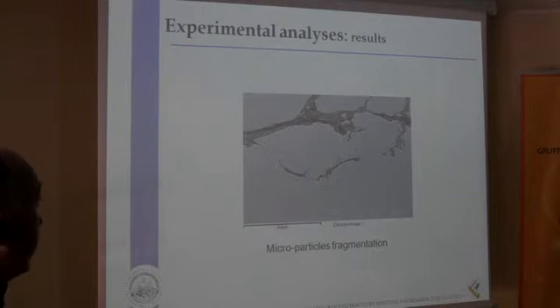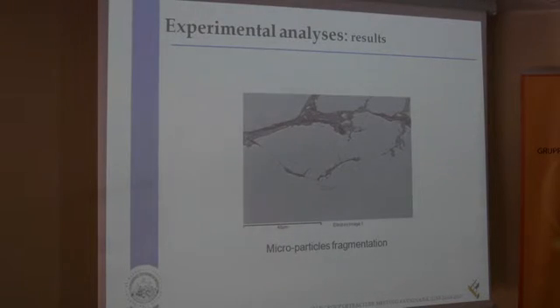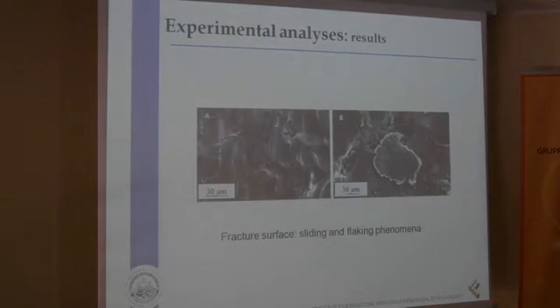It is interesting that this phenomenon was also observed by Matsunaga during a torsion test on bearing steel. The ring was finally broken after immersion in liquid nitrogen to observe its fracture surface, on which evident sliding and flaking phenomena were observed, which are typical of sliding mode propagation.